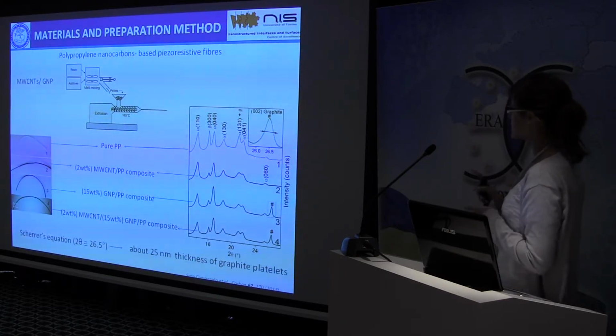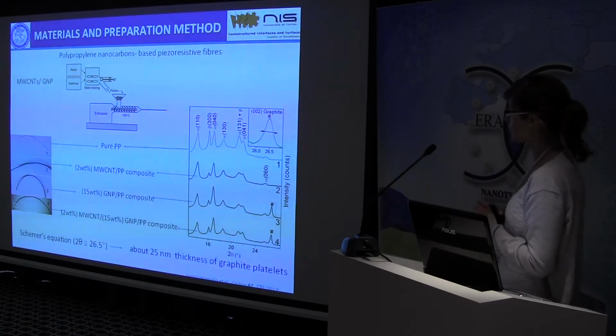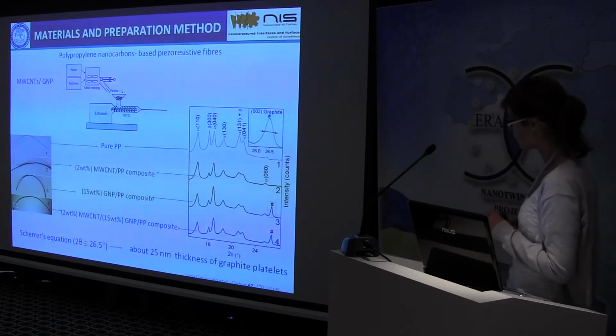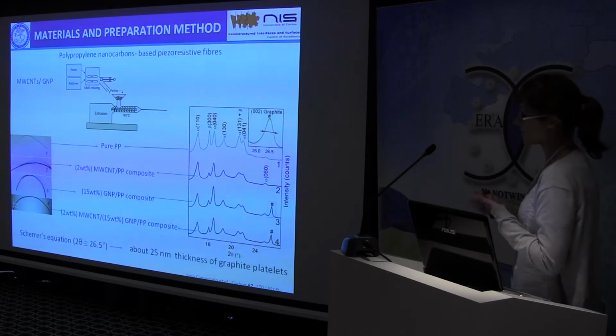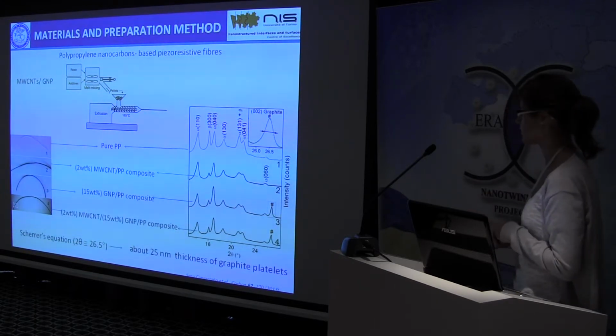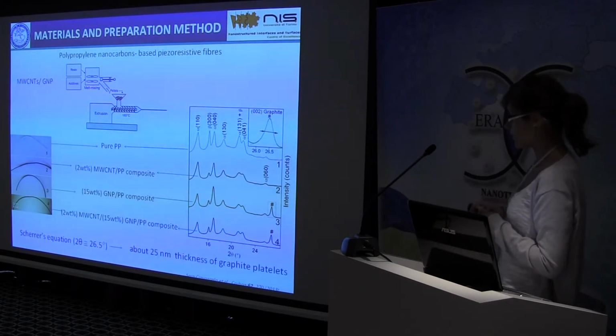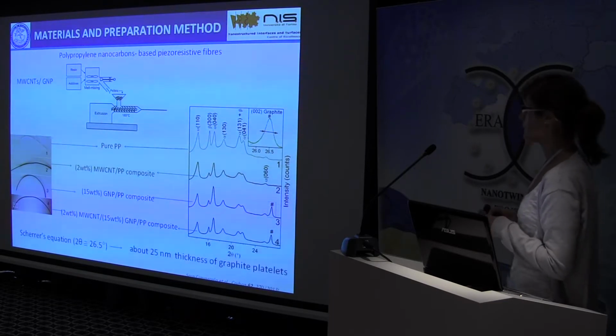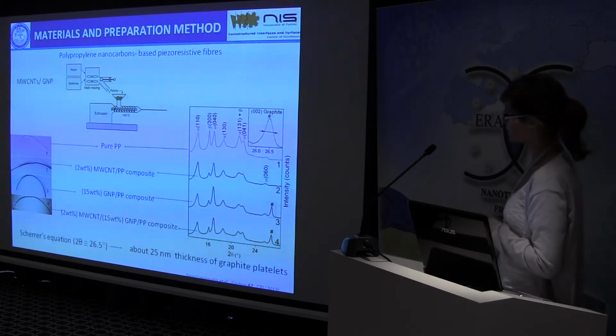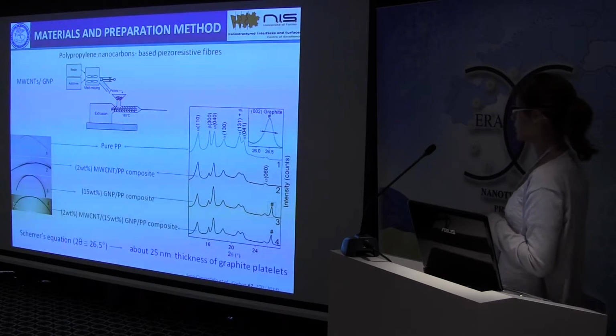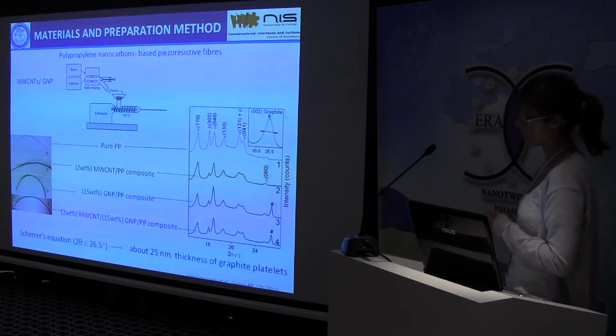So knowing the peak at 26.5 degrees, we applied the Scherrer equation and we tried to evaluate the thickness of the graphite platelets, which is about 25 nanometers, and this value is very close to the thickness of pure graphite nanoplatelets.